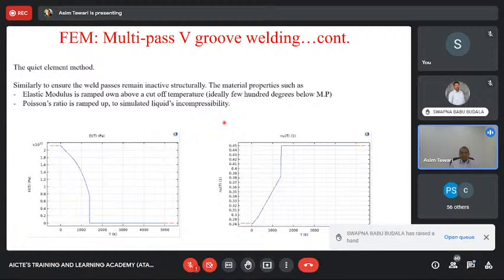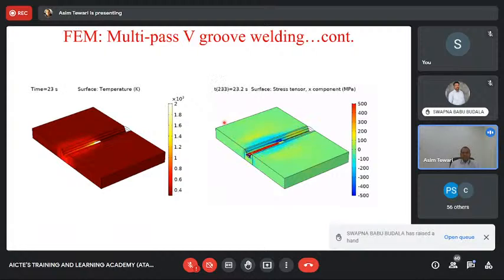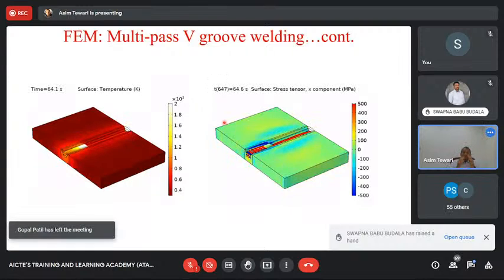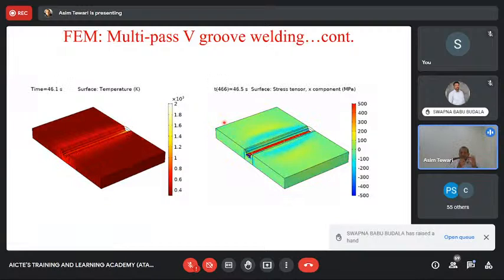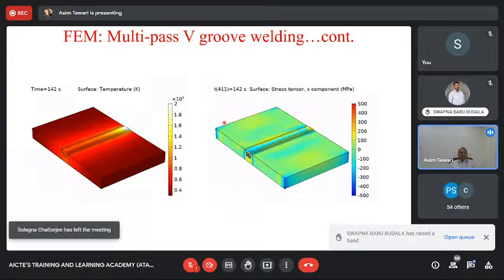And now what you realize is that the temperature is also causing the properties to change. As you heat the material, the yield stress falls, the elastic stiffness falls, the Young's modulus falls. And thus you have to take into account all these complex things at the same time. Not just the heat transfer and the eigenstrains, but the stresses also, because the stiffness is changing. And stresses are related to strain by the stiffness, right? So now this is how the actual residual stress variations can be seen